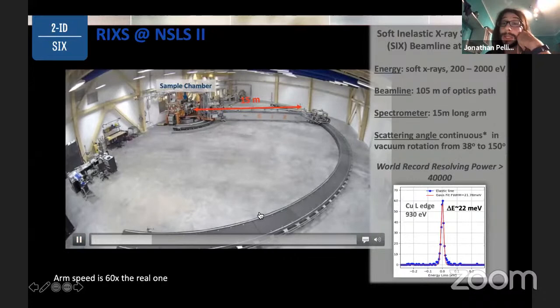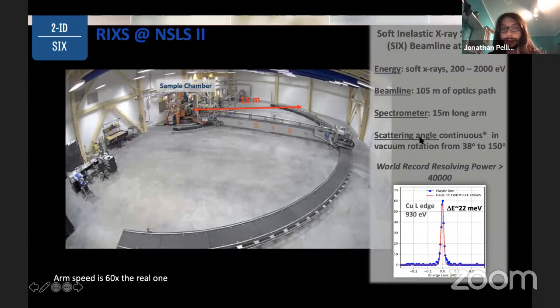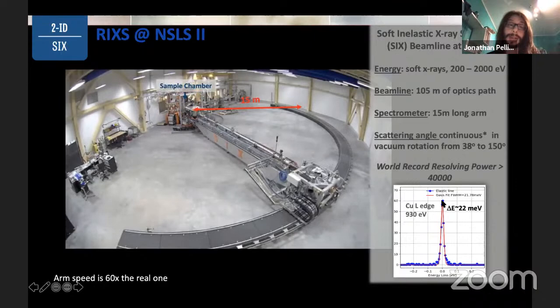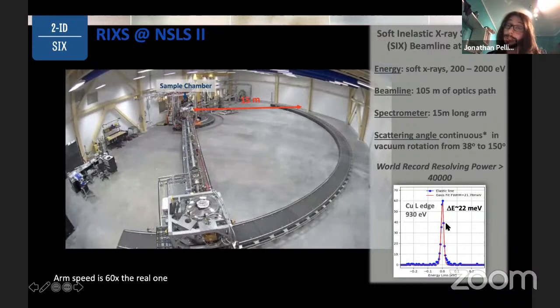Additionally, at our beamline at NSLS II, we also set the new world record in terms of energy resolution. And we achieved 22 milli electron volt at the copper L edge, which is actually pretty good. It's still a bit far from conventional neutron scattering experiments, but we will work on getting better.